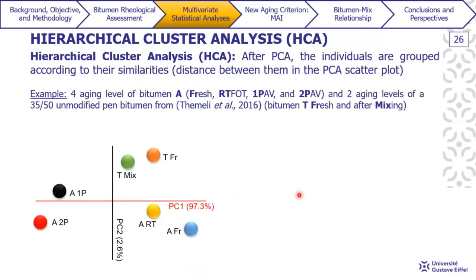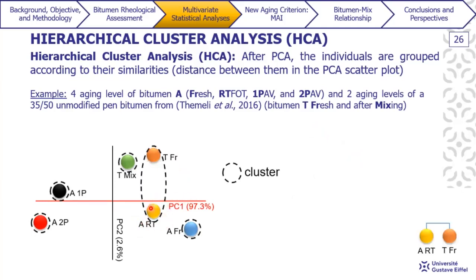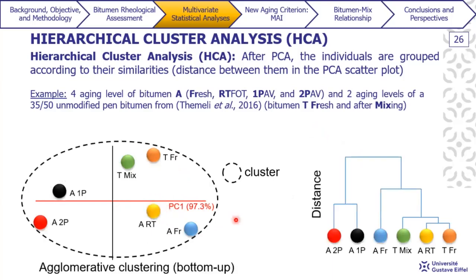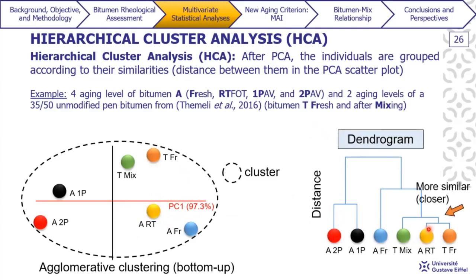Now let's jump to hierarchical cluster analysis, which is usually a complementary analysis that is done after PCA, where individuals are grouped according to their similarities. In this case, their distance between them in the PCA scatter plot. So here we go back to our sample scatter plot. Initially we consider that each individual is a cluster, and then we start merging them together. And as we keep merging, we also have the dendrogram here.